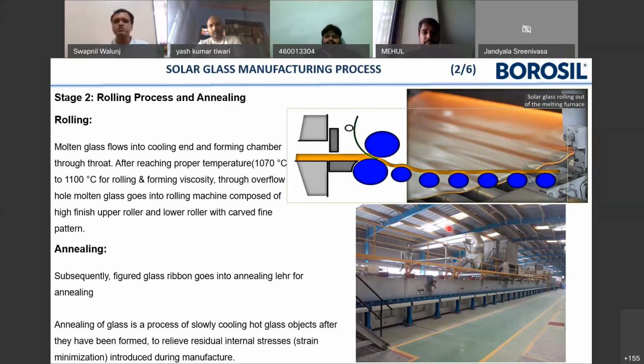The next process is called annealing. Annealing slowly cools down the hot glass after it is formed out of the furnace. Since it has been hot, there are certain stresses involved in this glass. By annealing, we relieve those stresses so that the strain inside the glass is minimized, and the glass is good for the next manufacturing process. So we have seen rolling and annealing as the next step after glass formation.